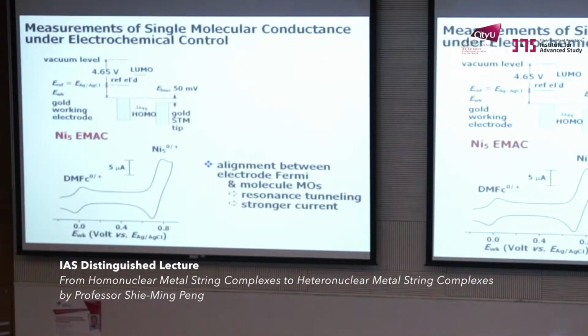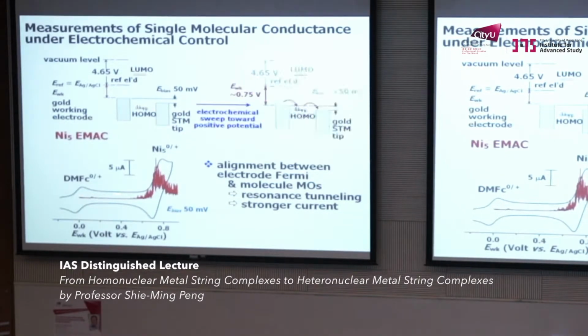For example, here is the electrochemical potential. When we scan, this is the so-called before oxidation. After oxidation, the current will be different. When the resonance happens, we have this resonant tunneling and get big current. So we now can get a spectrum. You can know where the HOMO of the metal string is.